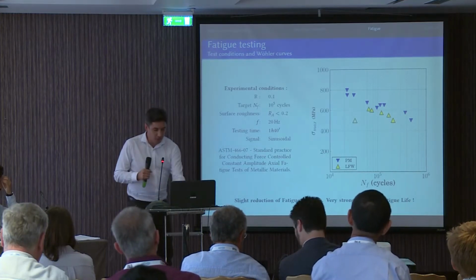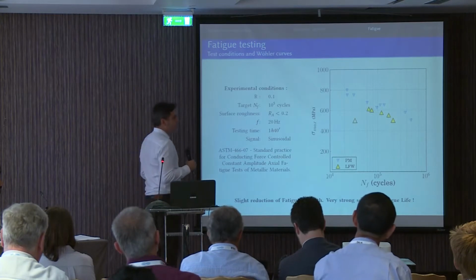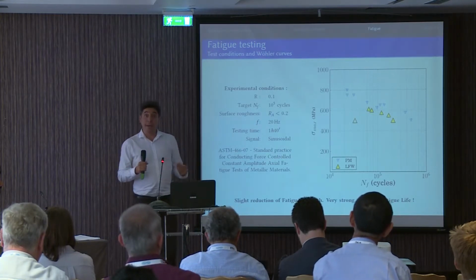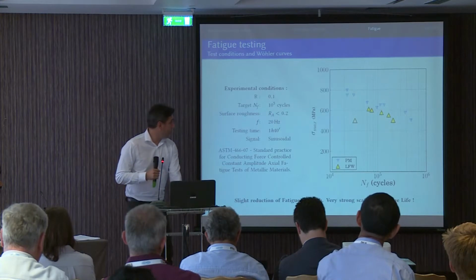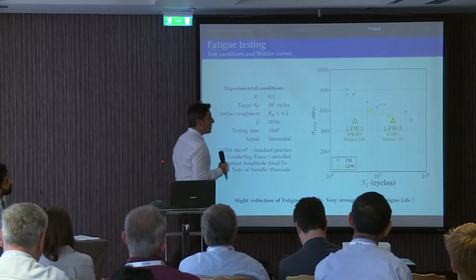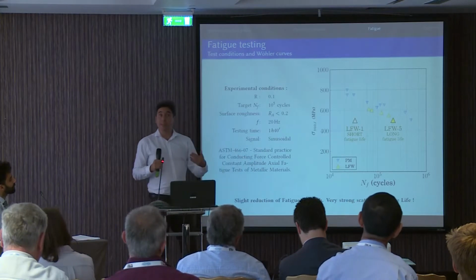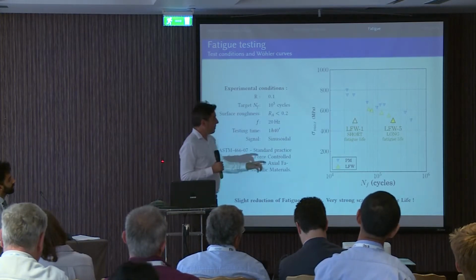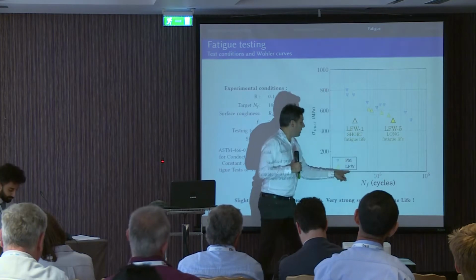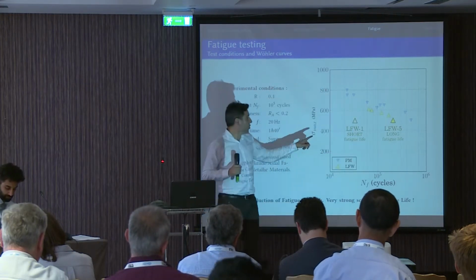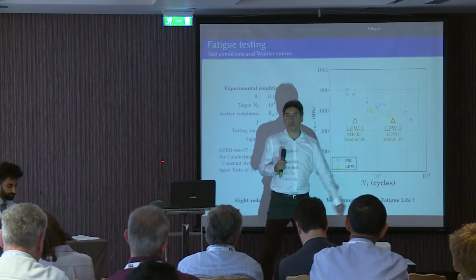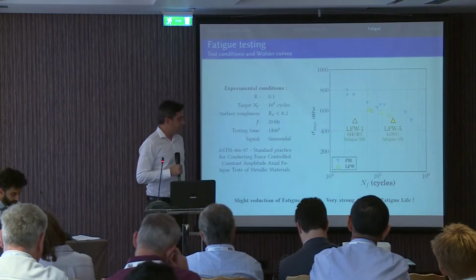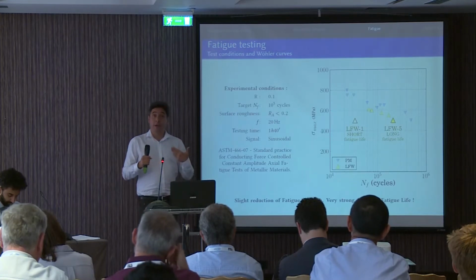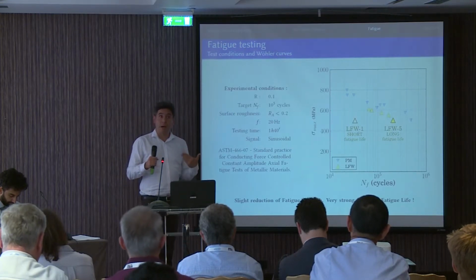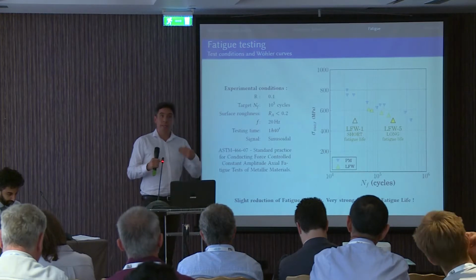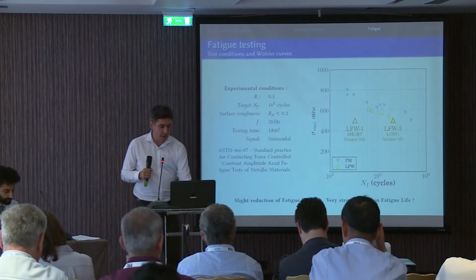But if we take a look at the cross-welded specimens, we can see that it's compromised with a very high fatigue life scatter. For instance, these two specimens, the 1 and 5, were tested at the same stress level. But if you pay attention here, the life is very, very different. So we have a short life specimen and a long life specimen, the 1 and 5. So we're testing a cross-welded structure in fatigue, and we would like to know where in this structure the fracture takes place.